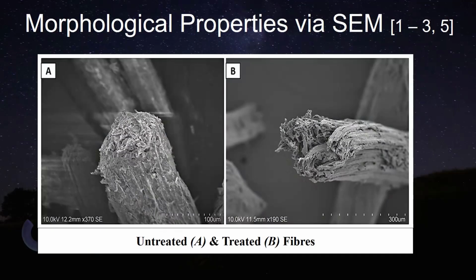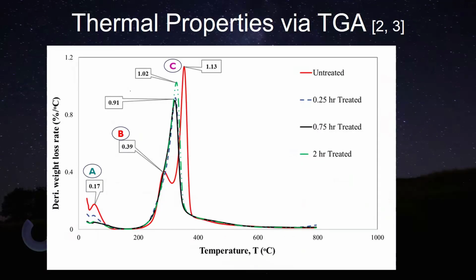So when we were convinced with that, then we did the thermal properties test through thermogravimetric analysis, TGA. And you can see I marked 3 places in the graph, A, B, and C. A is the presence of moisture, B is the presence of hemicellulose, and C is the presence of the cellulose itself. So we can see that only the untreated fiber has those three distinct peaks. After the treatment, all those hemicellulose has been gone. That's why there is no distinct peak over there. So this is another way to prove that after the treatment, hemicellulose has been gone.